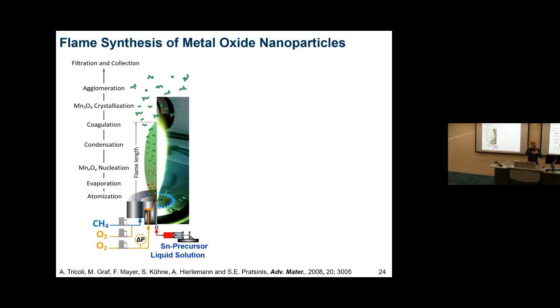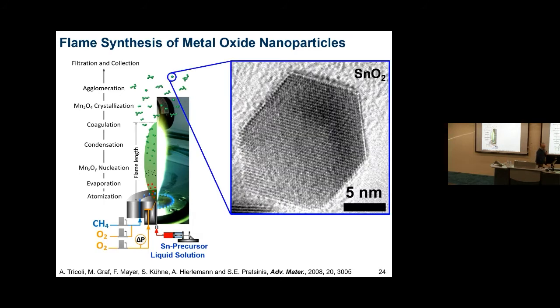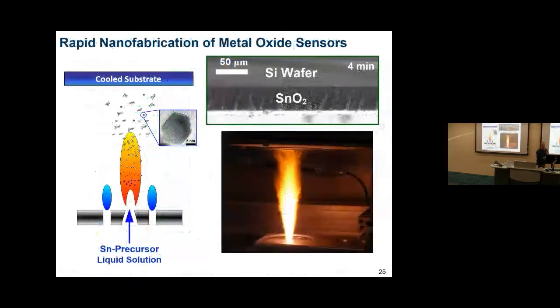And then you can use the aerosol deposition, for example this is a tin oxide crystal, to deposit it on a surface very rapidly. This is the deposition on a silicon wafer. You don't have to be so close, you can be quite far if you want. And you can see a very thick film deposited in a short time.